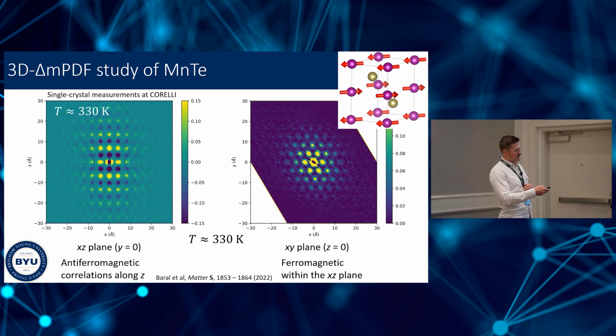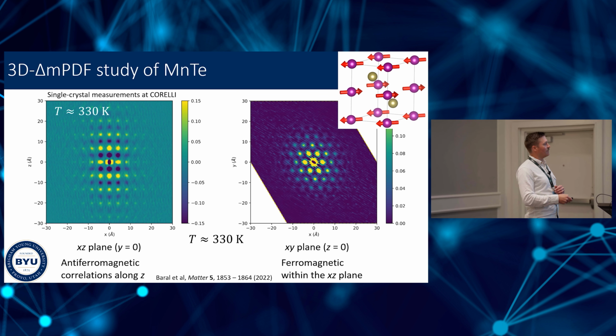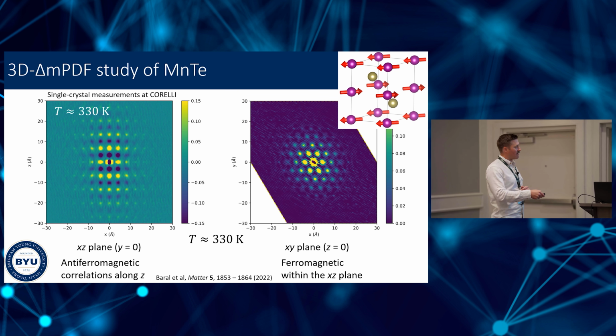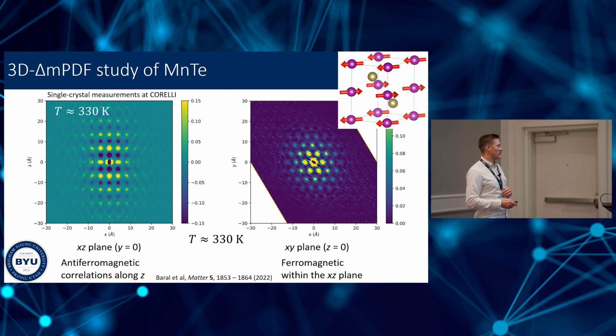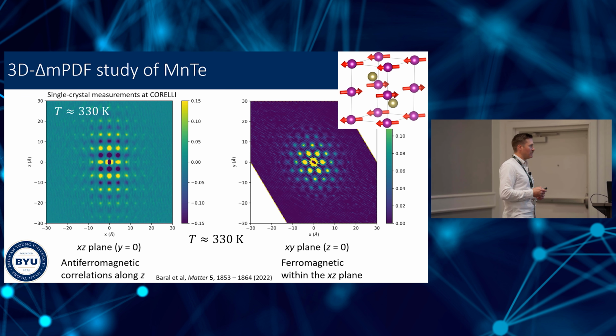But what you'll notice here is the correlation length along C is noticeably longer than it is in the AB plane. All right, and we can in fact take these line cuts and fit a correlation length and all that. And our single crystal data ended up being very, very similar to what we got from our powder data. So that was nice to see that agreement.